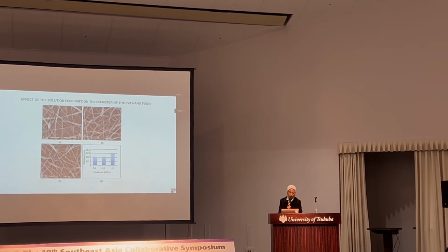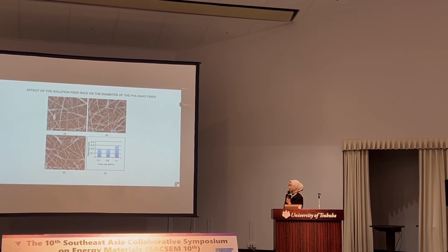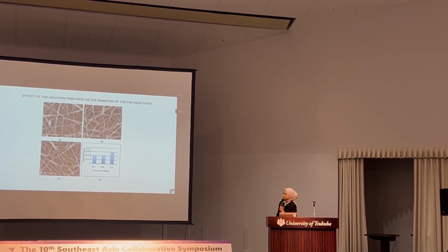Three, when the feed rate of the solution increases, the diameter increases. Maybe the solution droplet volume at the end of the tip is increased. The bigger the droplet, the bigger the diameter of the nanofiber.